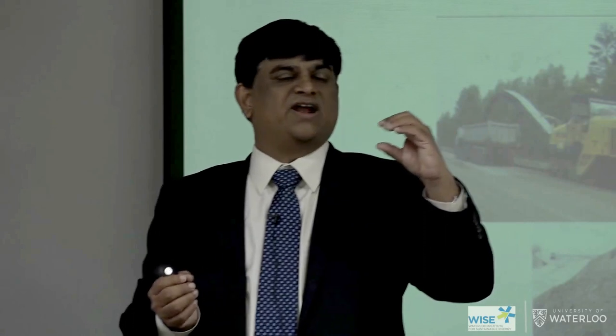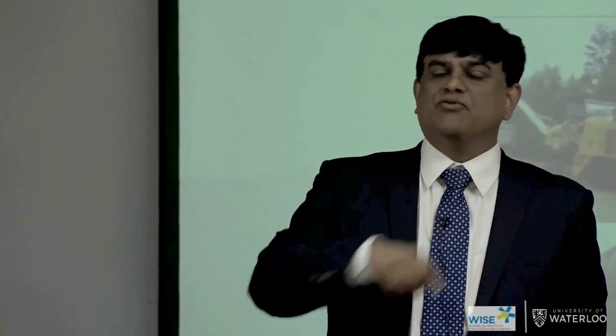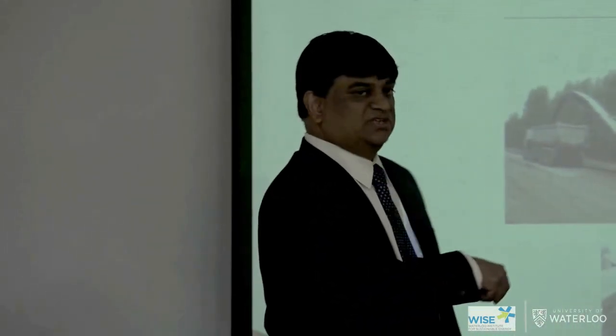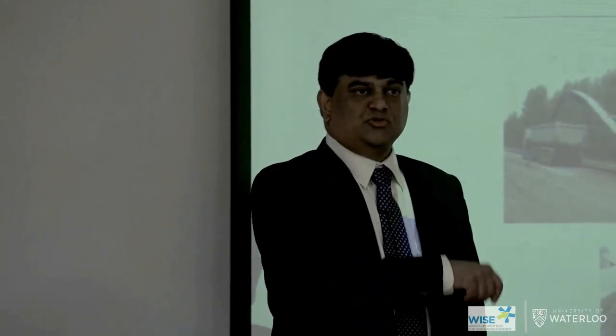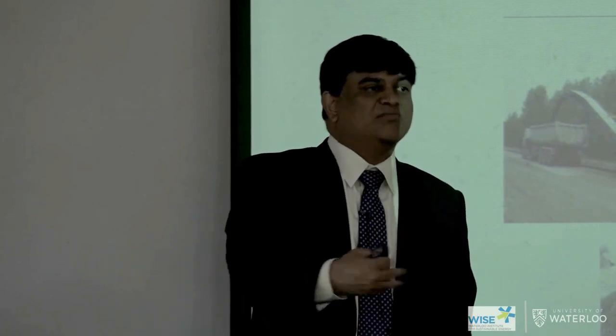And sometimes ettringite can bulk up to 2 times its original volume. So a lot of times the roads started heaving right in the middle. You know, the roads started breaking up like this. And when we did all the forensic investigation, we found out the natural soil has sulfates. But we didn't screen for them. So if I do have sulfates, I wouldn't use this material as a base material, because this has too much calcium, because it's already cemented material, right?